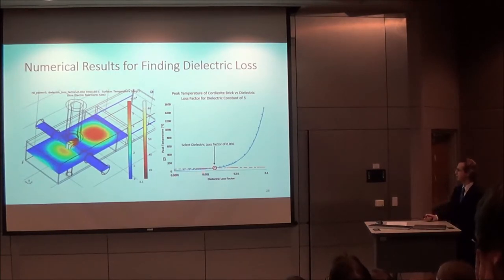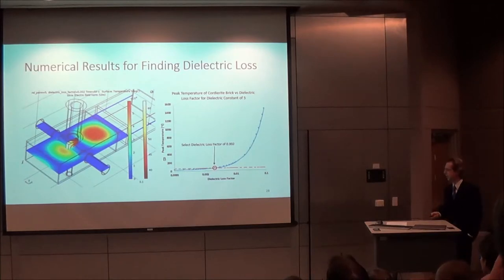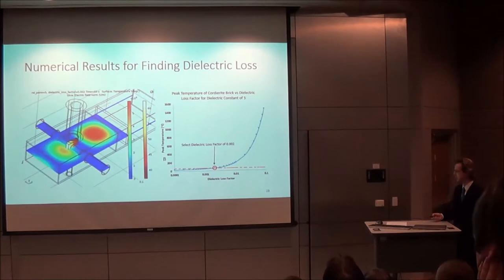This is the parametric sweep where we have the dielectric loss factor on the horizontal axis and the peak temperature after 60 seconds of heating on the vertical. And so the experimental value for this particular study was plotted on this orange dashed line, and where it intersects with the parametric sweep line, that is the dielectric loss factor that we can say is a pretty good representation of this material.